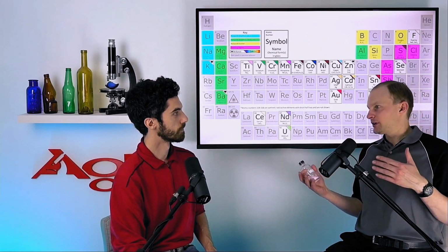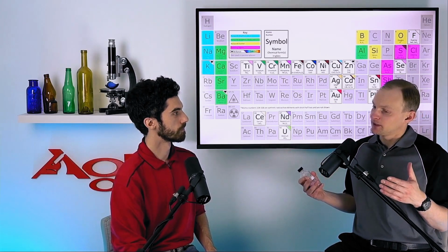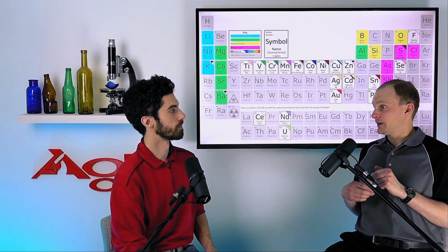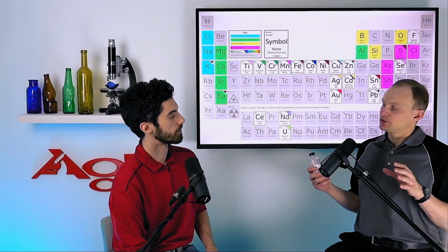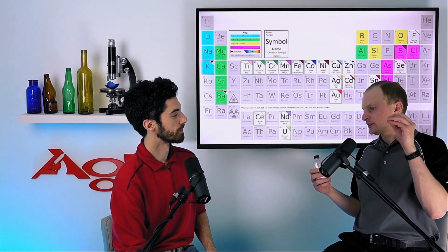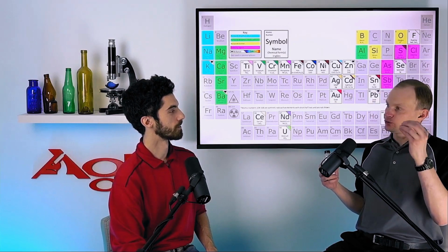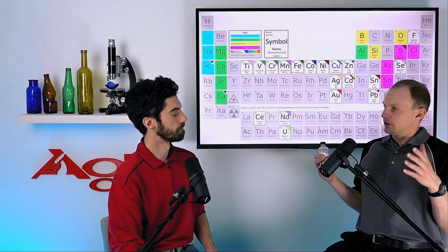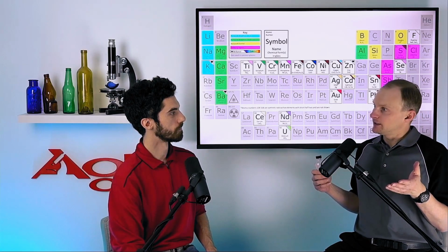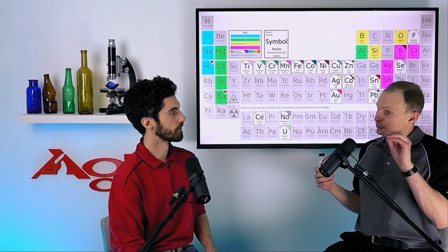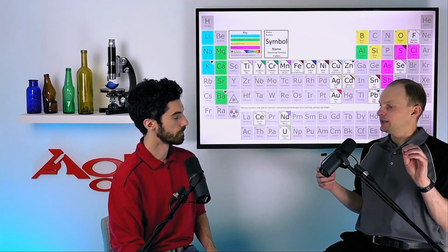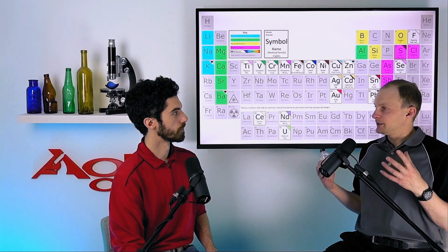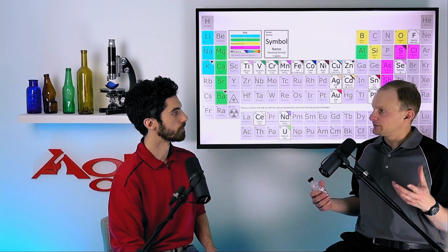So we play a little bit of a trick on your eyes. Turns out your eyes are really bad at seeing faint shades of gray. So what we're going to do is add in little bits of other colors to balance out that greenish color, or sometimes a little bit of yellowy color, that you can get from iron. For container glass, we typically add a little bit of cobalt, which makes blue, or a little bit of selenium, which makes pink. Those are relatively inexpensive ingredients.